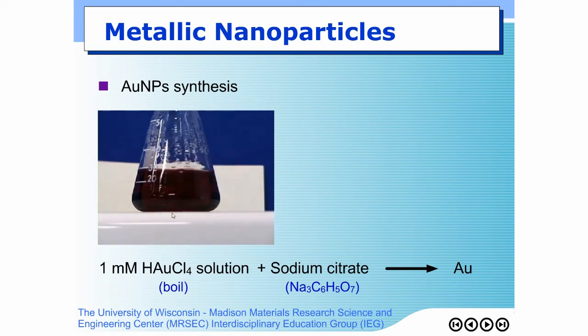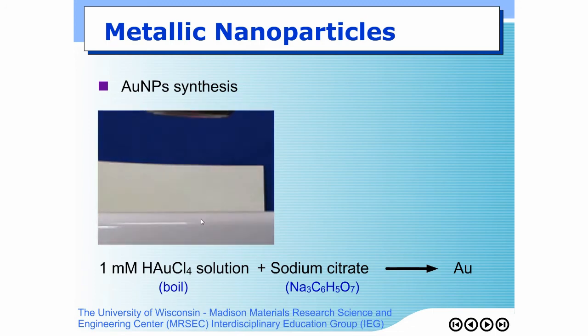You have to understand that the change in color signifies the change in particle size. So when you see the color change, the particles become larger and larger. So what you observe here is not only nucleation. Basically, you observe growth. Nucleation occurs within a very short period of time, but what you observe mostly will be growth. So if we compare nucleation and growth, growth is more important. Growth is the more dominating process that you need to control.